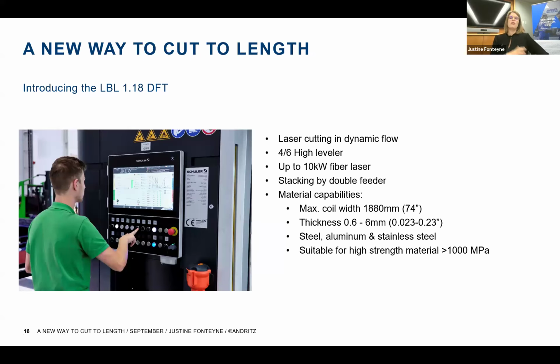Our laser blanking line runs in dynamic flow. So that is what we tag the continuous cutting. Our line can be equipped with a 4-high leveler or a high precision leveler with 6 levels with support rolls. We can integrate up to 10 kilowatt lasers. So depending on the thickness of your material, we define which one makes the most sense, starting at 4. And as I mentioned before, we have either the feeder as a single solution, or we add another one to make it a double feeder. We can cover coils with a maximum width of 74 inches, and the maximum thickness would be 0.23 inches.